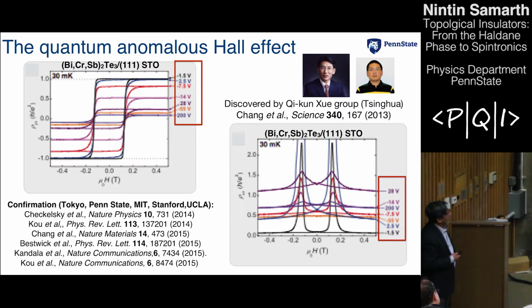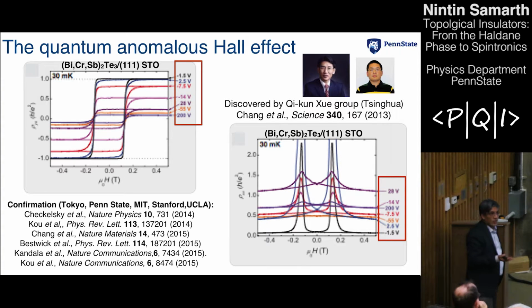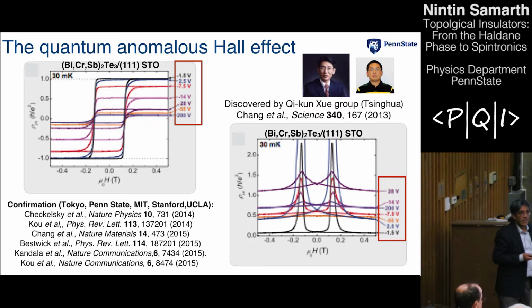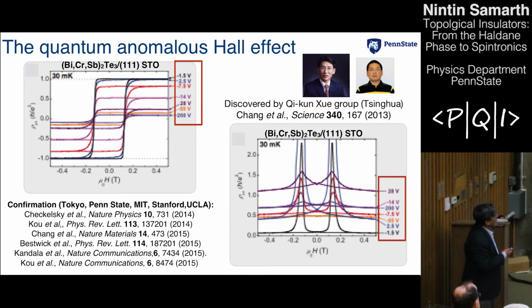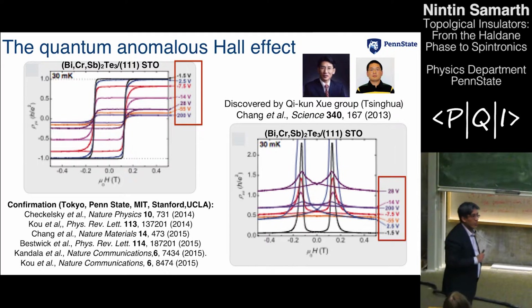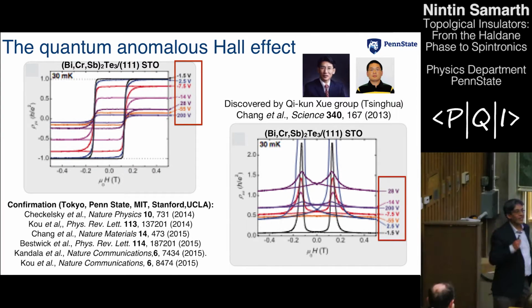And they found that if you made such a sample and you tuned the chemical potential, so you apply a voltage to the back of the sample, using this capacitor technique I talked about, and then you can adjust this chemical potential. When the chemical potential goes into that gap that has been opened by the breaking of time reversal symmetry, then at very low temperatures, rho yx, which is the Hall resistance, is quantized precisely to h over e squared. Now, when I say precisely, in this initial experiment published in Science, it actually wasn't precise. They weren't too careful about trying to show that it was precise.